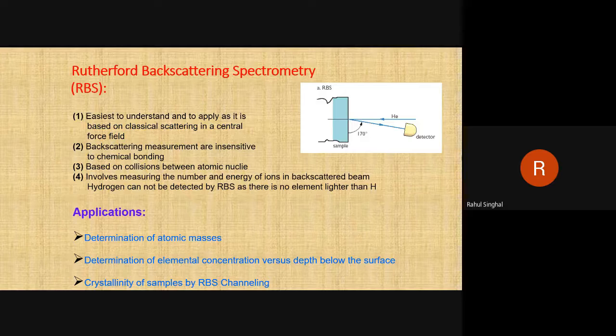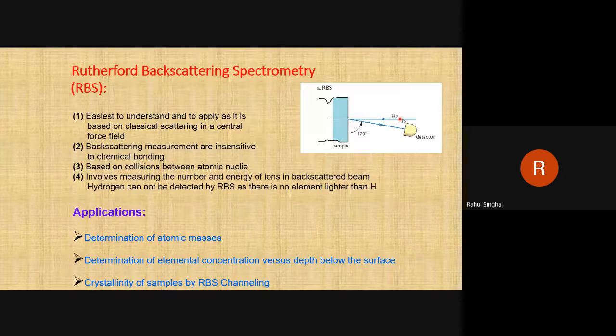So I told you that suppose you have hydrogen in your sample. Once a helium ion comes from this direction, I'll take the mouse and change the pointer option to the laser button. So this helium ion is coming in this direction and you have hydrogen present in your material. Once the helium atom has a collision, both the helium and hydrogen may go forward. It means helium ions will not come back; they will go in the forward direction. So in order to measure the hydrogen, you will not put the detector here. You will keep the detector somewhere here.